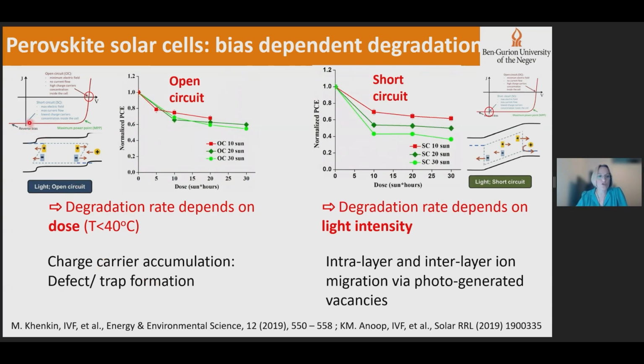However, if you use short circuit, so these conditions, you see a very clear difference between the different illumination intensities, which means that in this case, the degradation rate depends on light intensity. That is the rate of causing damage and not the accumulated damage. If again, you want to consider that, this is probably photo-generated vacancies at the active layer that cause intralayer and interlayer massive ion migration that occurs and causes the cell degradation. This is just one example of how we can use natural sunlight for studies of stability of perovskite solar cells.